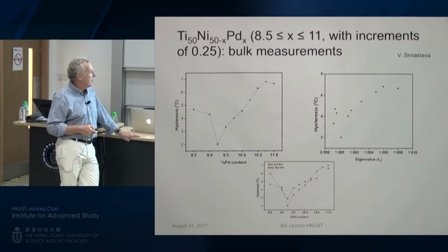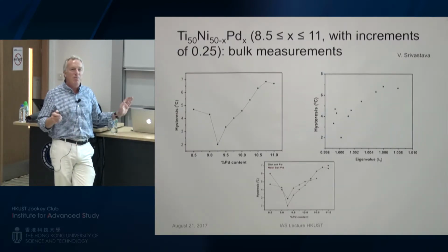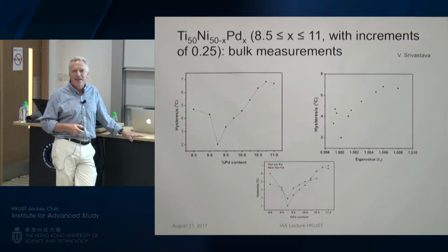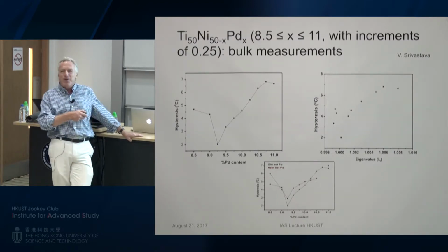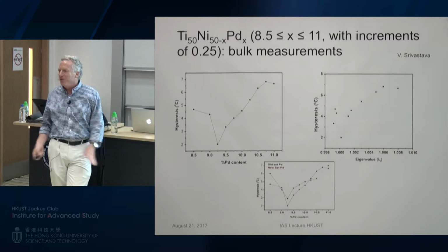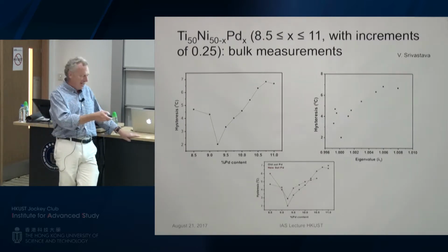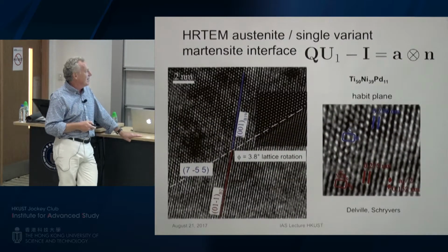And if you really want to get your lambda 2 equals 1 alloy, you should go 1/4% compositional changes. Now, if you go 1/8% compositional changes, I have no idea, maybe it can go even lower, I have no idea. But it is very sensitive to composition.